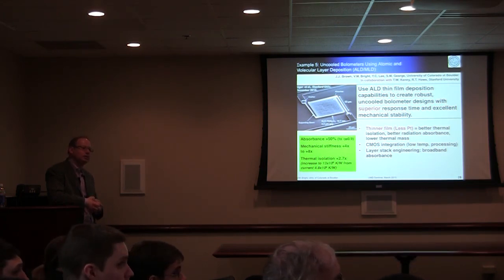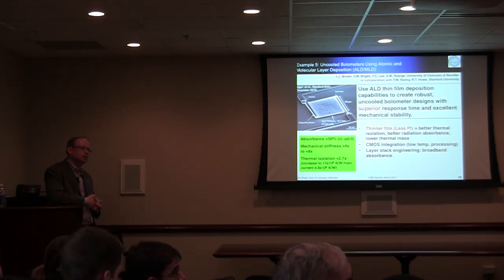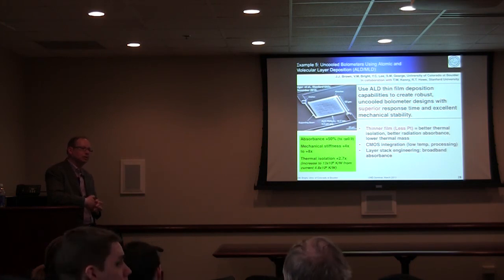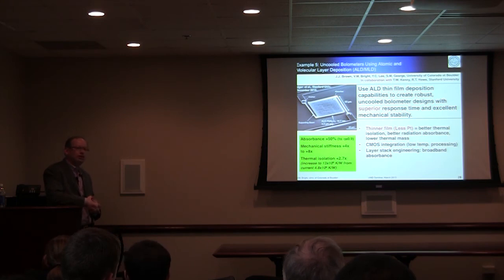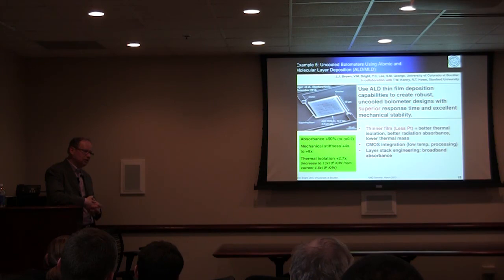About MLD, it seems like this is a way to use some interesting polymer coatings. Is there anything everybody's really familiar with that can be deposited, like polystyrene? I'm really not an expert in that. The alucone-based, the original MLD film, is more of a nylon type of material. The zincones, I'm not sure what exactly they are. But one thing you're right about is that for flexible substrates, as a barrier coating, it works extremely well, but not by itself. It works as a superlattice of organic and inorganic.